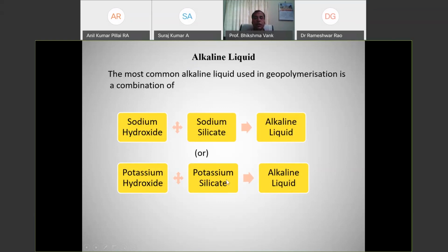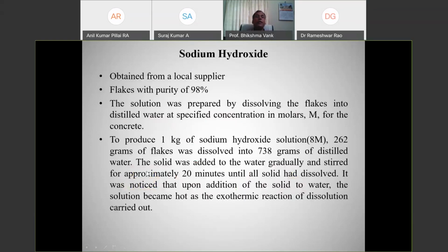This is a little costlier. So this combination we have taken, and then the procedure is there for how to select and take flakes from the market: sodium hydroxide, sodium silicate, obtained from a local supplier, flakes with a purity of 98%. Sodium hydroxide was prepared. We have to prepare the solution. All these procedures are given: to produce 1 kg of sodium hydroxide solution of 8 molarity, 262 grams of flakes was dissolved into 738 grams of distilled water.